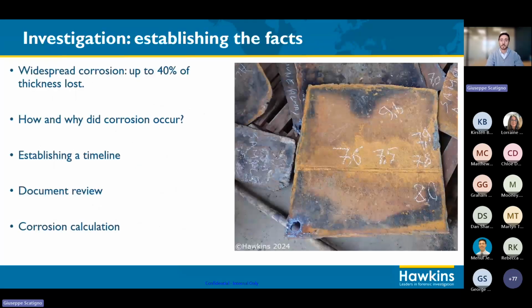issues may arise. So I visited the dry dock in which the vessel was being repaired to carry out UT testing, ultrasonic thickness gauge testing of the hull to understand how much of it had corroded, and compare it with the survey that had been carried. And we knew that on average, corrosion had spread to the majority of the hull and had corroded to about 40% of the initial thickness.